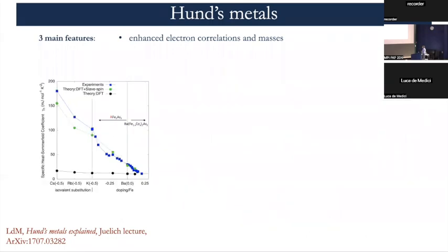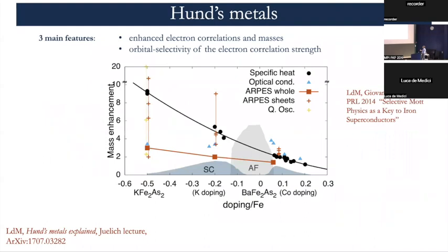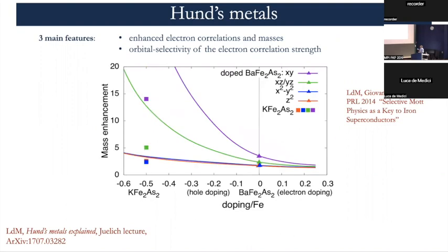Another result that we have shown is that this happens because the electrons, not only going towards half filling, get more and more correlated, but the system tends to orbital selectivity. So depending on the d orbital character of each electron, they get more correlated or less correlated within the d shell. So you have coexisting heavy and light electrons, and this selectivity is really well captured by experiment. I can't analyze all this, but it comes up in different probes. And so you see the values spread more and more, and this is due to the increasing spreading of the correlation strength among the different electrons in the d shells. And it's very well captured by theory once again. So you really have the d_xy, for instance, orbitals, which are very heavy, and they coexist with other orbitals from the same d shell, which are much less correlated.